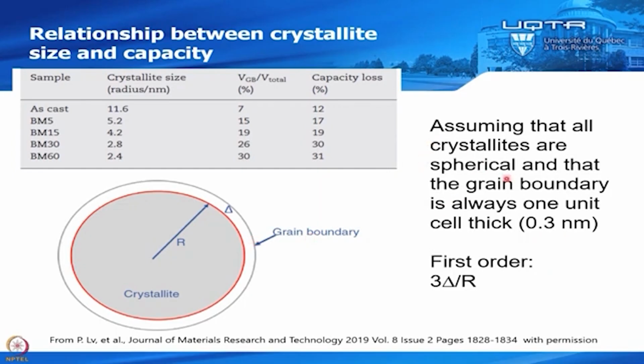And then if we assume that the crystallites are spherical, and of course the crystallite size that we measure by X-ray is an average, okay? But we assume that all the particles are at this average, and we assume that all of them have the same grain boundary thickness, okay? And then we could calculate the volume of that grain boundary compared to the total volume of the particle. So this is a very simple equation. So on first order, this is 3 times the thickness of the grain boundary over the radius of the crystallite.